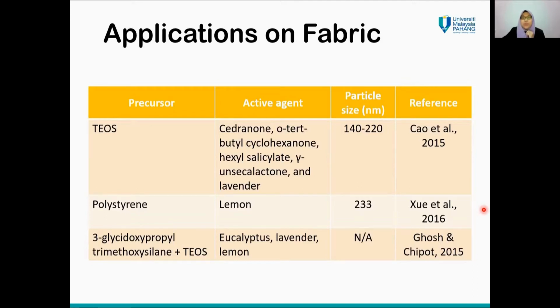Another study, done by Ghosh and Chipot in 2015, used a natural cross-linking agent, beta-cyclodextrin, as inclusion compound to embed the aroma into cotton and cotton polyester fabrics using sol gel prepared from 3-glycidoxypropyl trimethoxysilane and also tetraethoxysilane. The retention of eucalyptus, lavender, and lemon aromas for the finished fabrics was found to decrease over 6 weeks and 6 washings. Moreover, an increase in tensile strength of the cotton polyester fabric was observed after the application of the finish.